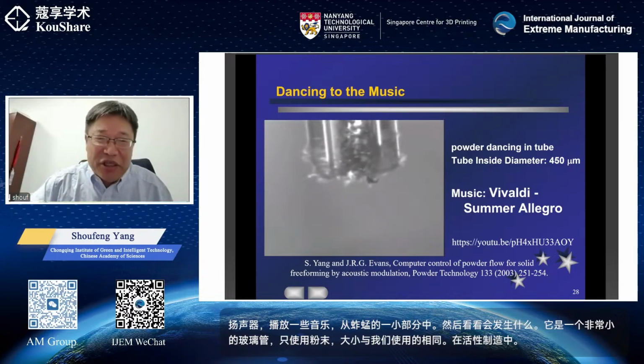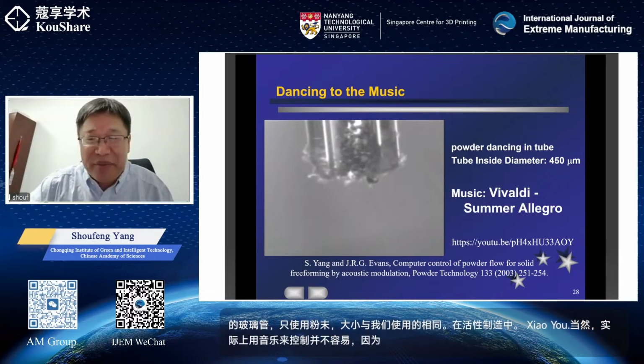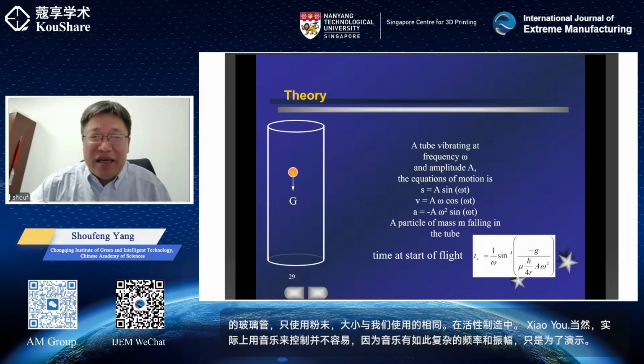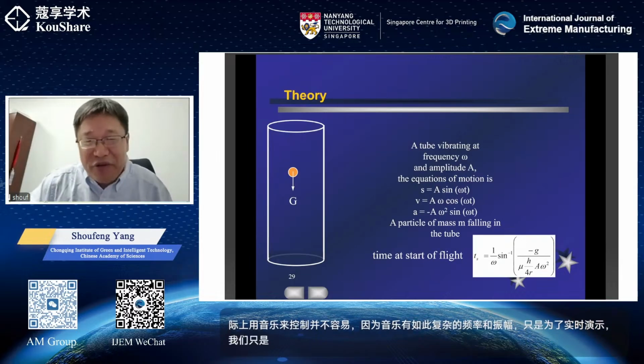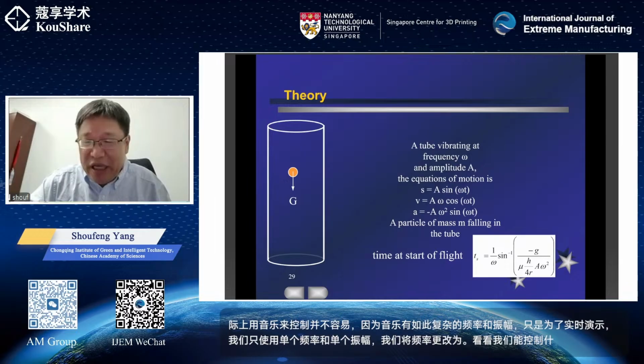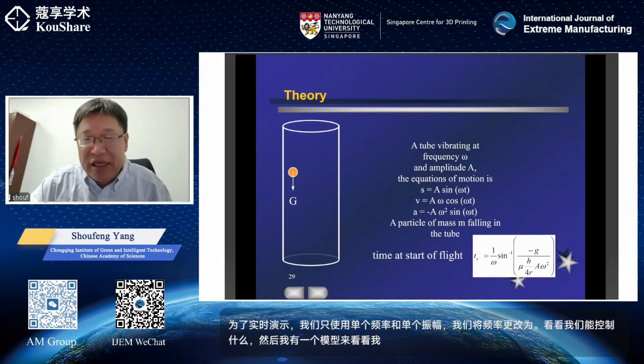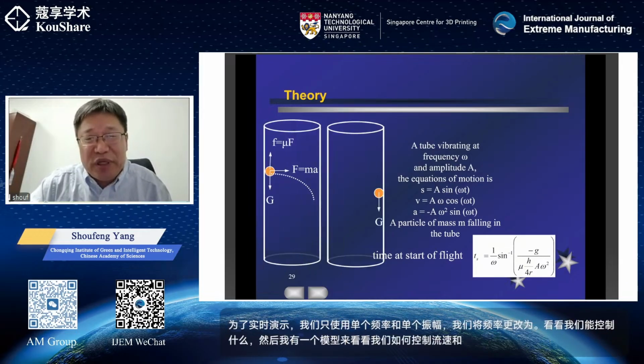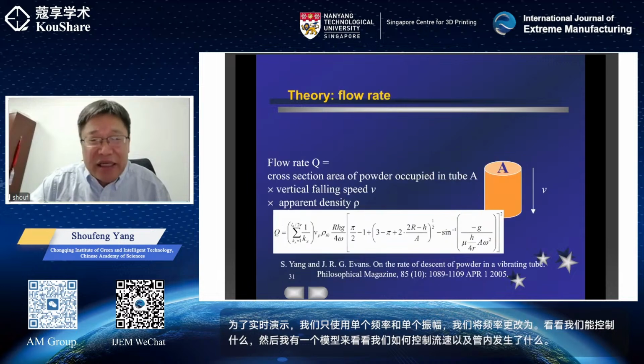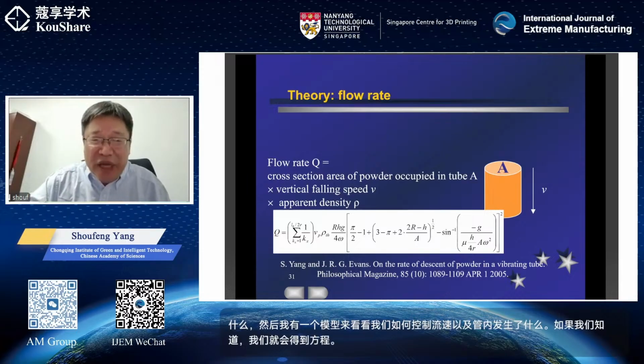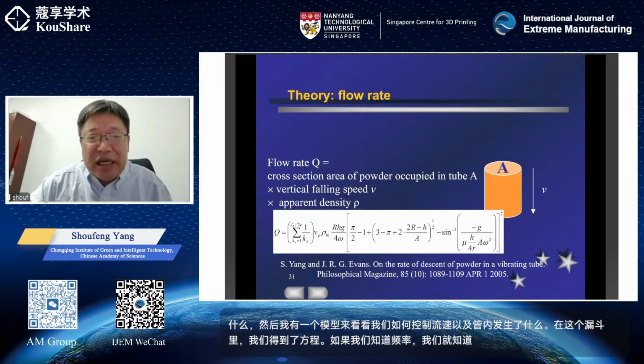Sure, actually, it's not easy to control with music because music has such complex frequency and amplitude. Just for demonstration. In real time, we just use a single frequency and a single amplitude. But we change the frequency to see what we can control. Then we built a model to see how we control this flow rate and what happened inside this hopper. And we get the equation. If we know the frequency, if we know the particle size, we can predict the flow rate.